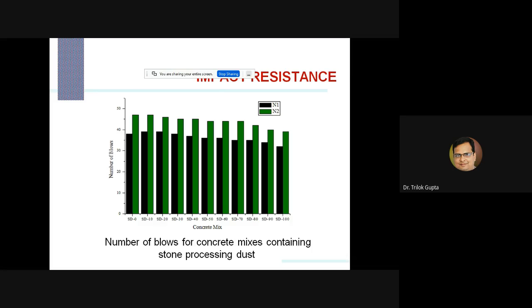Now we come to the impact resistance. This figure shows the number of blows for the concrete containing stone processing dust. This black graph shows the N1, that is the number of blows required at the time of first crack, and this green N2 represents the number of blows required for the ultimate failure. From this figure, we can visualize that up to 40%, similar to the control mix, it is not much more affected.